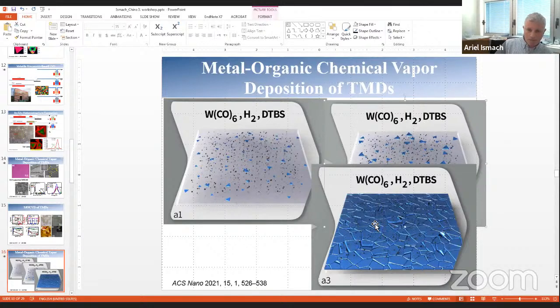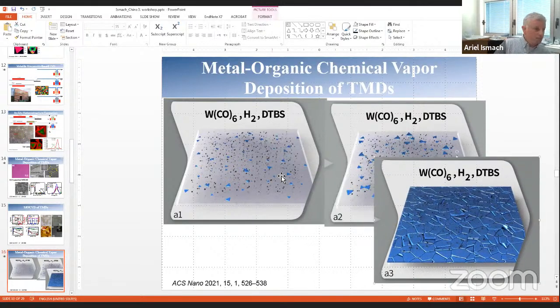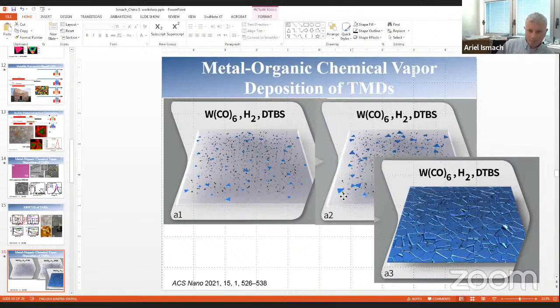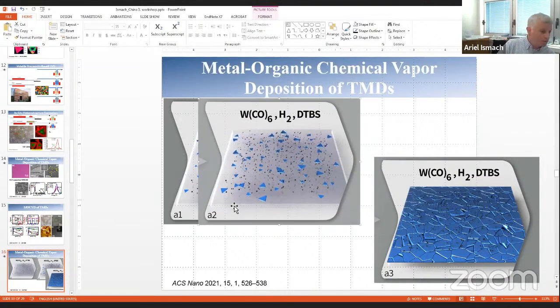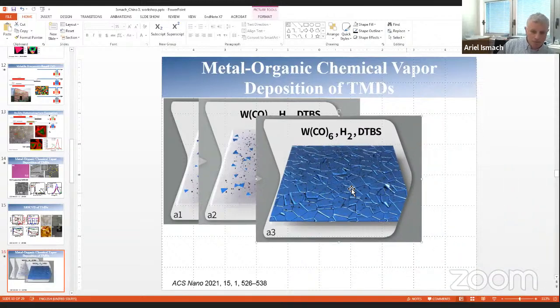Okay, so that was an animation anyway. In a standard growth, you have the nucleation of the TMDs, in this case tungsten disulfide, in blue, and then you have some carbon impurities along the way. These carbon impurities act as further nucleation points, and are also encapsulated in the films, therefore lowering the crystallinity and the quality of the film. As the growth continues, you end up with a continuous film with very small domains and carbon impurities, as I showed you in the beginning.